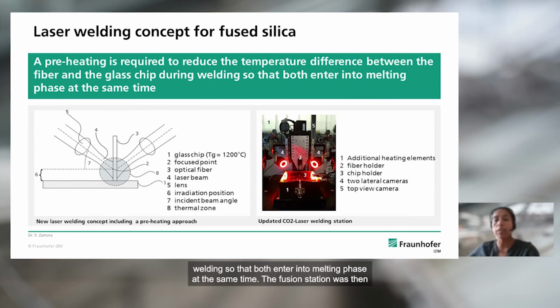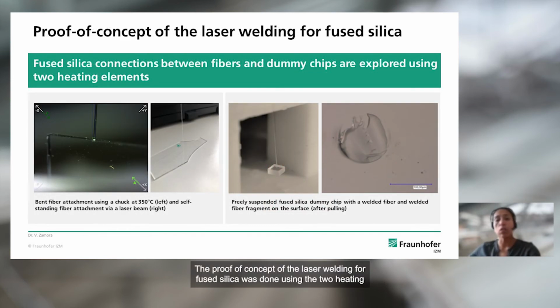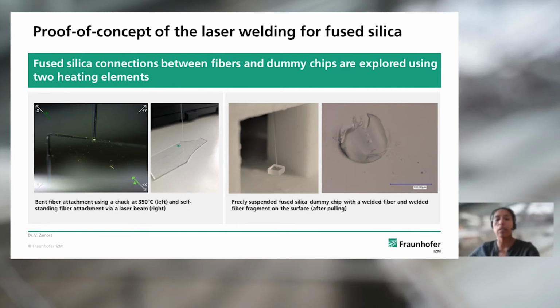The fusion station was then upgraded to incorporate 2 heating elements, laser and chuck, new fiber and chip holders, and also 3 additional cameras. The proof of concept of the laser welding for fused silica was done using the 2 heating elements. The results are as follows. The fiber bent out of position using the planar heating chuck while it remained stable by using a second laser beam. This test led to the conclusion that the laser will be used as a heat source.